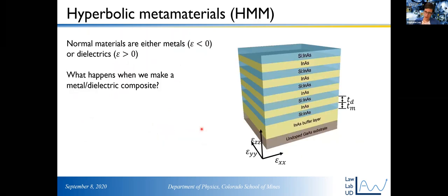So I'm going to now skip over a whole bunch of device-related stuff and talk about something that I think is really very cool. So I told you already, materials are either metals with a negative permittivity or dielectrics with a positive permittivity. But you can actually make a metal dielectric composite. So imagine that we grow a stack like this, right? This is what MBE is good at, stacking stuff up. So in this case, you grow a stack where each layer is really thin, much thinner than the wavelength of light. So we have a doped layer, this is a metal layer, then we have a dielectric layer, then a metal layer, then a dielectric, and a metal and a dielectric, and we stack all these up. And remember, they're each really, really thin. So when the light shines on this material, what it sees is a composite. It sees something that has metal parts and dielectric parts.